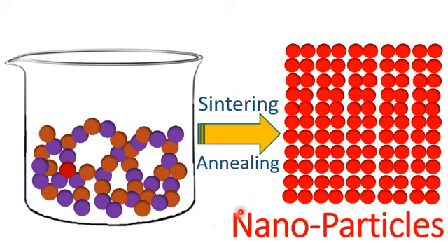Okay, if we anneal the iron oxide nanoparticles below the single phase formation temperature, like below 800 degrees centigrade, this will result in the formation of impure iron oxide nanoparticles. So in order to produce single phase nanoparticles, we need a specific sintering and annealing temperature.